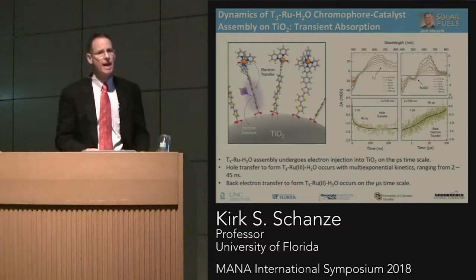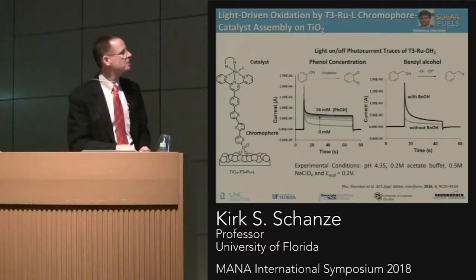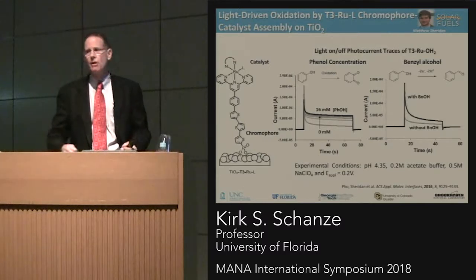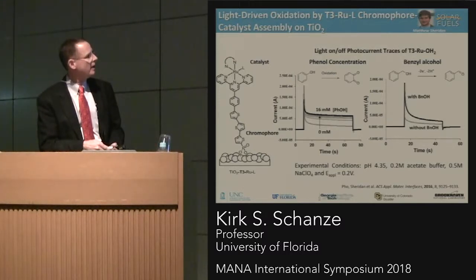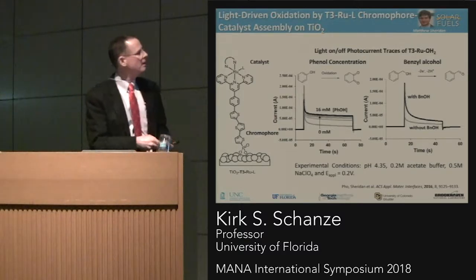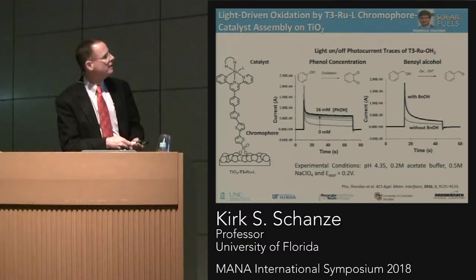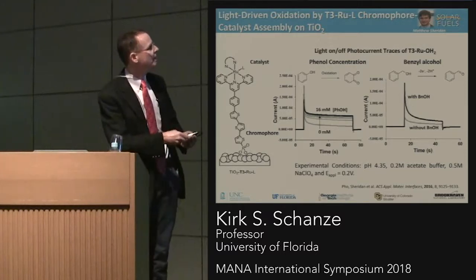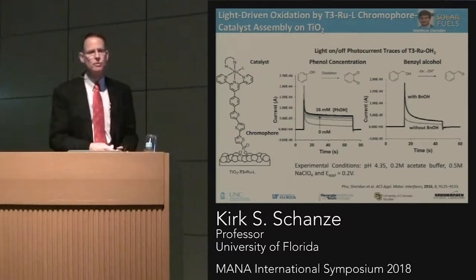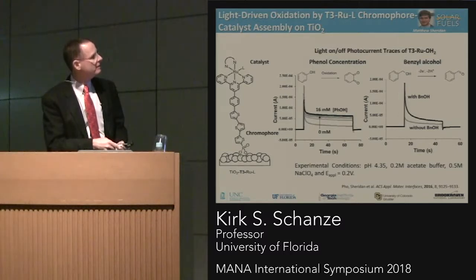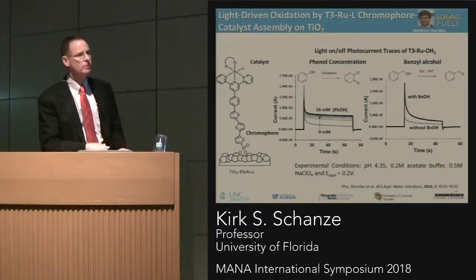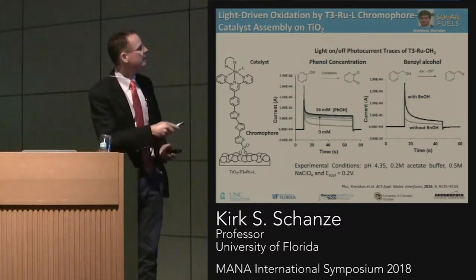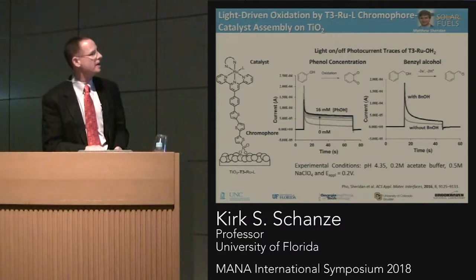The next question is, can they actually carry out the reactions that we would like to accomplish? And in order to study that, we go to much longer time scales using continuous light photolysis of photoelectrodes and monitoring current on time scales of seconds. What I'm showing you here are photocurrent traces for illumination of this assembly on a TiO2 electrode when we add various sacrificial reductants. By that, I mean organic substrates that can give up electrons to the electrode. And we can see that as we increase the amount of the sacrificial agent, the current comes up. So that does tell us that these assemblies are able to carry out oxidation reactions.